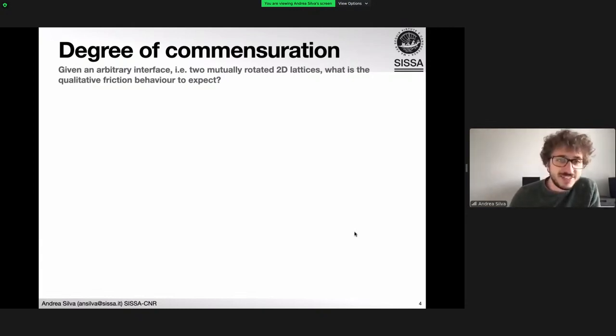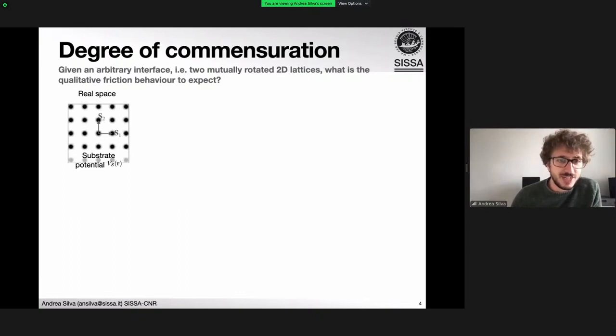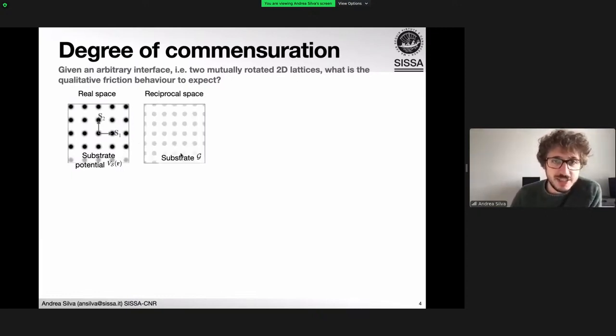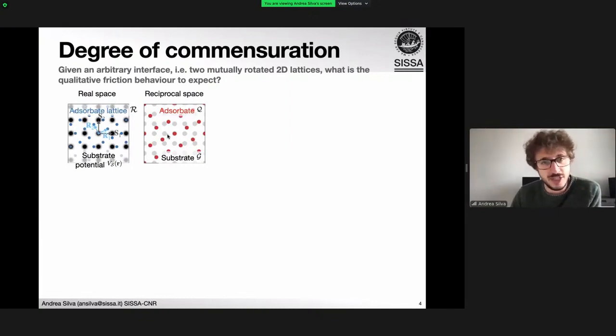But first, let's build a system. Our system is built from a substrate potential, which has a general form and is periodic with whatever periodicity we want it to be. And there is a reciprocal space associated to it, so the Fourier transform of the real space. So we put above the substrate our adsorbate, building our crystalline interface. And this would be a second lattice with a different periodicity that can be rotated at an angle and is associated with an adsorbate reciprocal lattice as well. So the red points here.